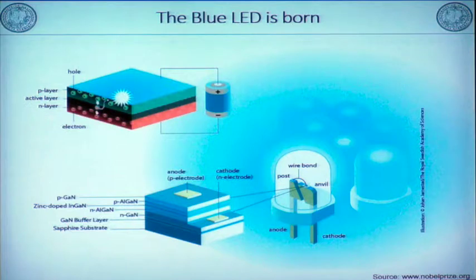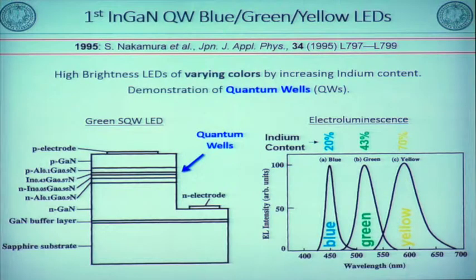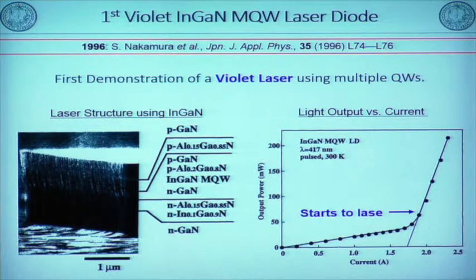So this is a Nobel Prize citation. You can see the basic LED structure is a substrate, N-type GaN, the active layer, and the P-type gallium nitride. Also in 95, we developed the first indium gallium nitride quantum well blue, green, and yellow LEDs. So this is now the basic structure of currently commercially available blue and green LEDs. All LED companies use this structure, with the indium gallium nitride quantum well. Also, in 96, we developed the first violet laser diode using an indium gallium nitride quantum well active layer.